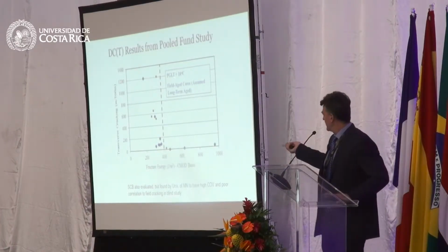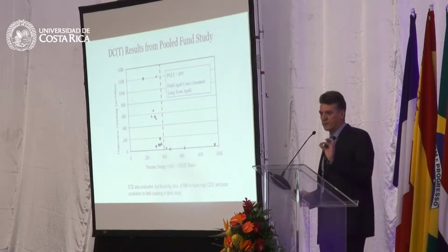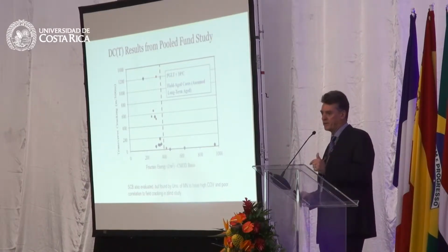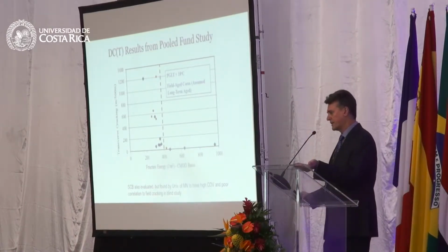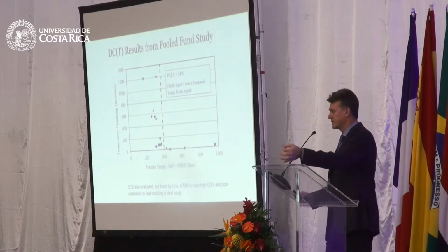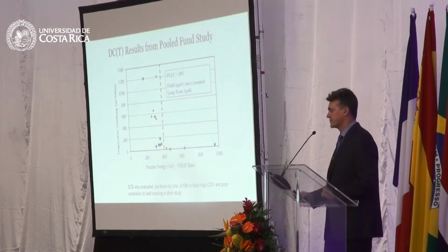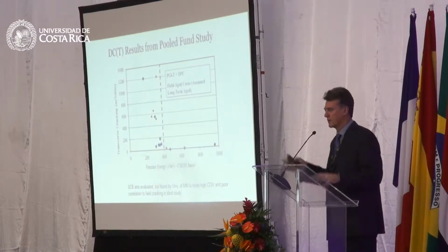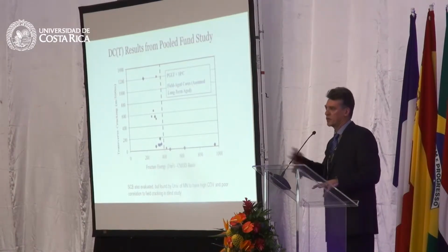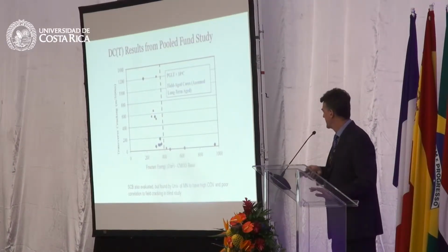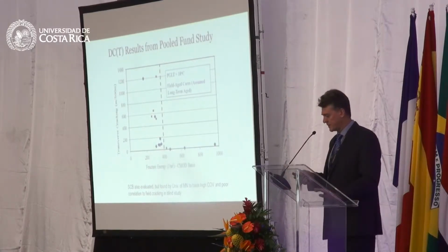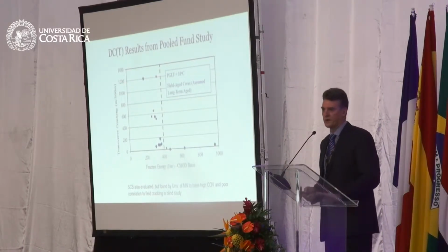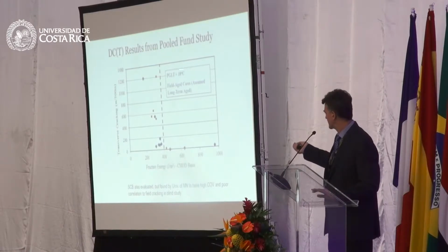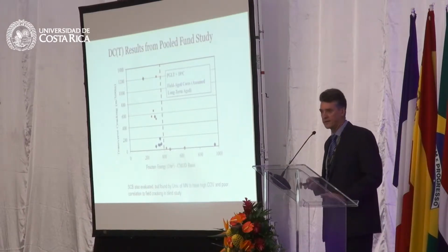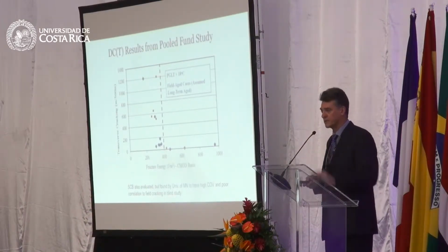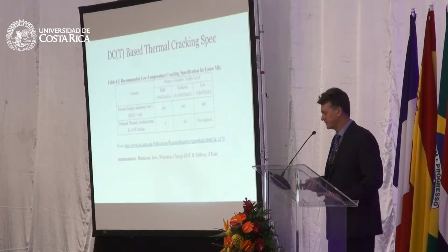The temperature you test at was similar to the philosophy of the bending beam rheometer. You look at the low temperature grade of the binder, add 10 degrees Celsius, and that's your test temperature. It puts you in that quasi-brittle range where there's lots of thermal cycles in cold climates around that temperature. We found results at that temperature correlated to field cracking a little bit better than using just the low temperature grade of the binder, where the material becomes quite glassy and brittle at that temperature.